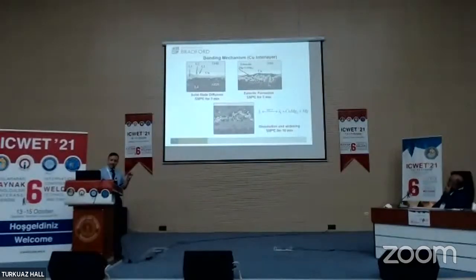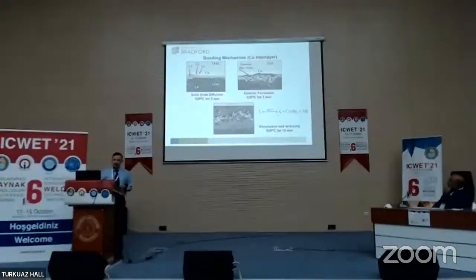And so this micrograph shows you a lot of white patches. These patches here are intermetallic compounds. So whenever we have dissimilar materials, we can expect to see these. We are trying to reduce these intermetallics or try to control them so that we can have good joint formation, but also somehow change the shape or the volume of these intermetallics.